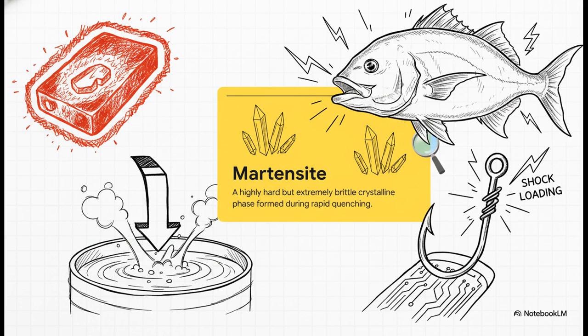To understand the stakes of that tempering process, we need to talk about martensite. When the steel is rapidly quenched, its structure transforms into this martensite phase. It's incredibly hard for sure, but also extremely brittle. Let me guess, if a cheap hook isn't properly tempered to stabilize this martensite, a massive shock loading from a GT strike is going to be completely disastrous. Spot on. It causes an immediate cleavage fracture. The hook won't even bend.